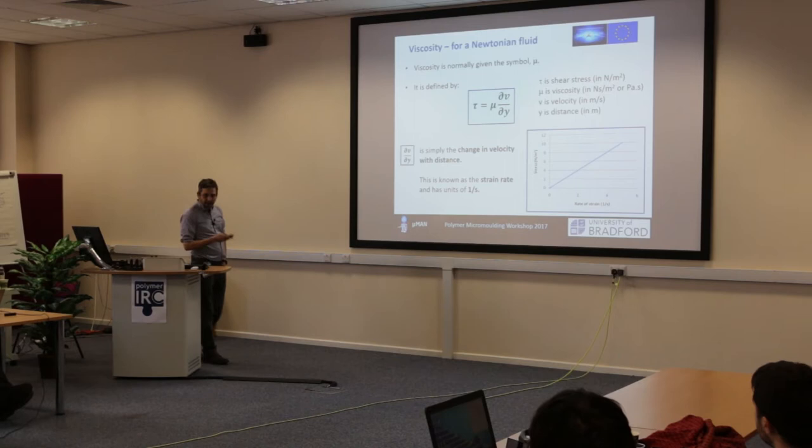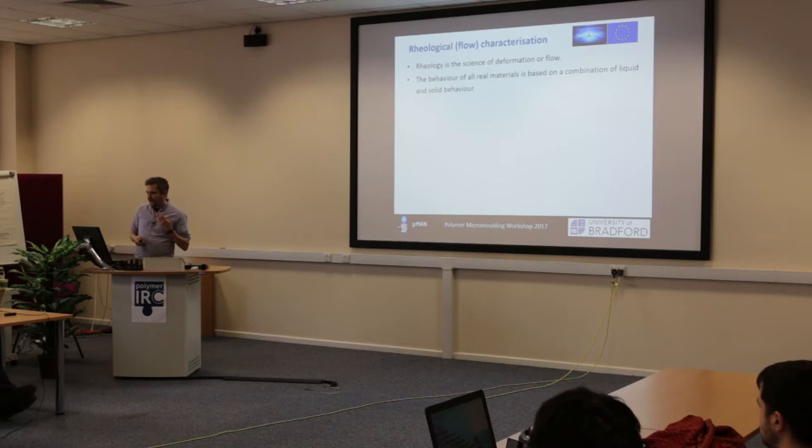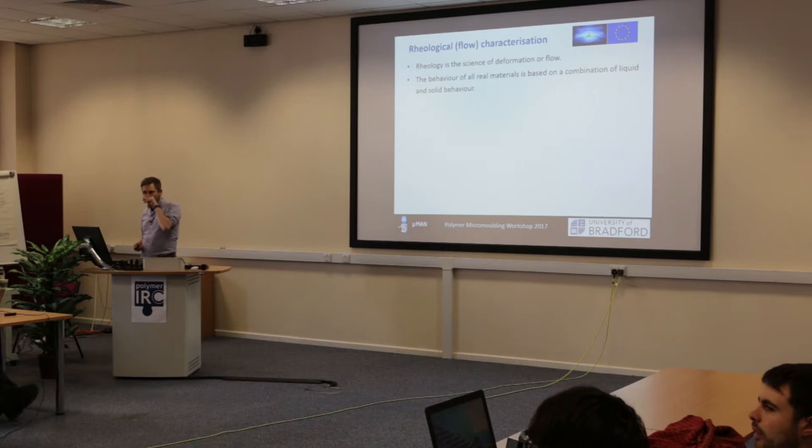Unfortunately, or fortunately for us, it doesn't work that way, I'm afraid. Rheology is pretty complex, and it's complex because the materials we look at aren't true solids and they're not true liquids, okay? So this Hookean notion of stress versus strain gives us Young's modulus, and this Newtonian notion of stress versus rate of strain gives us our viscosity, but it isn't true, okay? We have a combination of viscous and elastic behavior, okay? So these materials are known as non-Newtonian.